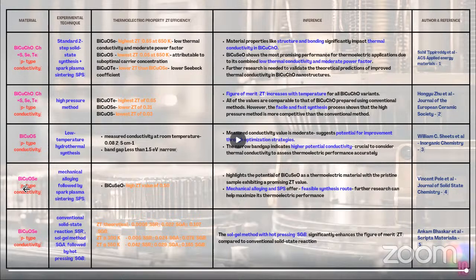This is crucial because efficient thermoelectric devices require both P-type and N-type materials for effective energy conversion. Number 2, experimental technique. Several synthesis methods are compared, including standard two-step solid state synthesis followed by spark plasma sintering, high pressure methods that utilize the extreme pressure to manipulate the material structure and potentially enhance the properties, hydrothermal process, mechanical alloying and sol gel process.